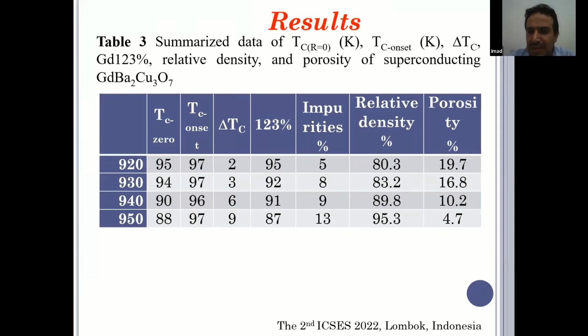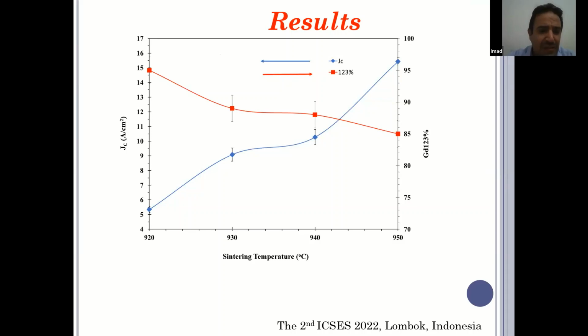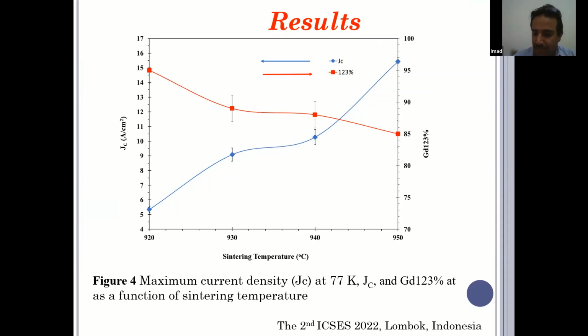But actually, we did something else. We managed to calculate the relative density and the porosity, and we found that the material gets a higher relative density as the sintering temperature increases, and the same for the porosity but in the opposite manner: porosity decreases as the sintering temperature increases. We also calculated the maximum current density as a function of sintering temperature, and found that it increases as the sintering temperature increases. These measurements were done at 77 Kelvin.